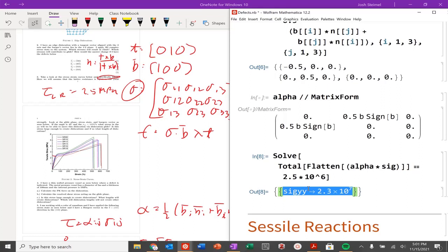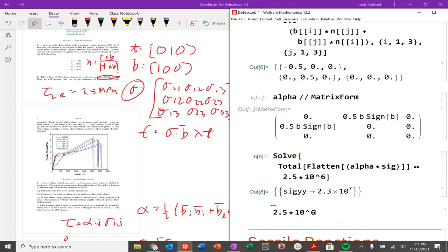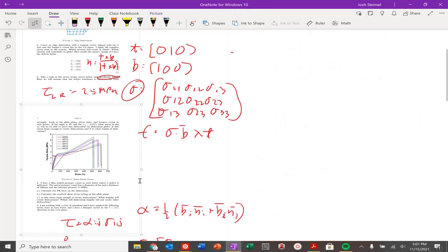That's new dislocation glide. Is the stress large enough to create dislocation? So again, once this is my resolved shear stress, now we're asked the question, are we able to essentially create or nucleate dislocations? So if we're nucleating these dislocations homogeneously, we have the following relationship, that my critical tau c is equal to G B over 2 pi L.